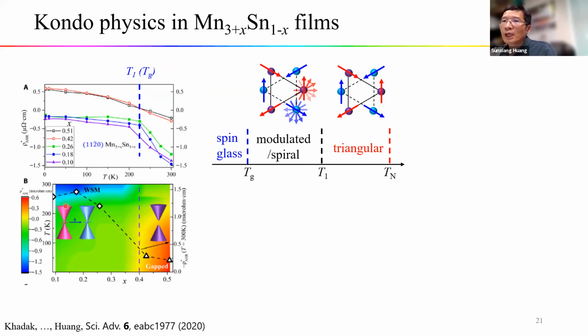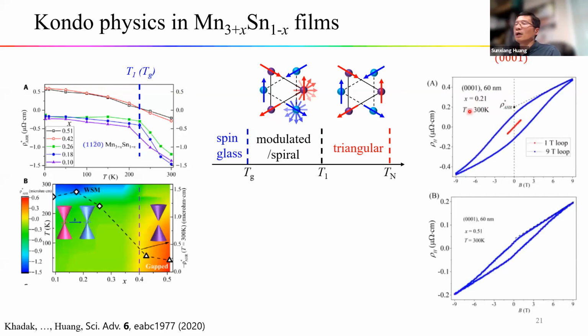The Kondo physics is similar for the (1120) and (0001) films, but for the Hall effect, the (0001) film shows quite different behaviors. The 1 Tesla loop of the Hall resistance shows no hysteresis and zero remnants, but the 9 Tesla loop shows clear hysteresis and finite remnants. If we subtract the linear background, we get the anomalous Hall contribution.